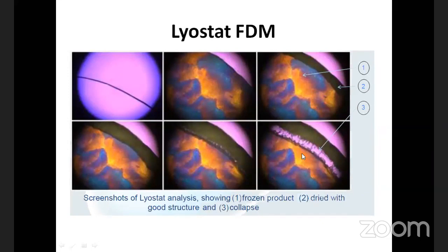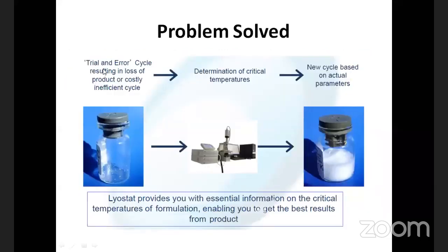So freeze drying microscopy is used as one of the best techniques to find out collapse temperatures. Usually what we do is we go for trial and error cycle development methods, where there is a high possibility of the product getting collapsed. So this is how the collapsed product looks like. We didn't find any cake inside this because we did not know about the critical temperature or collapse temperature. Any product processed without knowing such collapse temperatures or critical temperatures, this is what we are going to get. But if we know the collapse temperature and process the product below that temperature, obviously we are going to get a good appearance product.